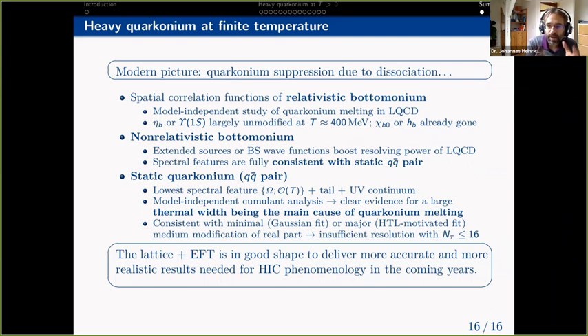And then we find spectral features where there is a very, very small mass shift for the bottomonia and a substantial width for the bottomonia. If you go to the static limit, where we keep these at fixed locations, we decompose the spectral function, do a model-independent cumulant analysis, and find evidence for a large thermal width, and then analyze it with different methods. And we find that we can't make a clear statement whether it is screened or not, but we can definitely make a statement that the imaginary part, which leads to dissociation, is important already at the crossover.